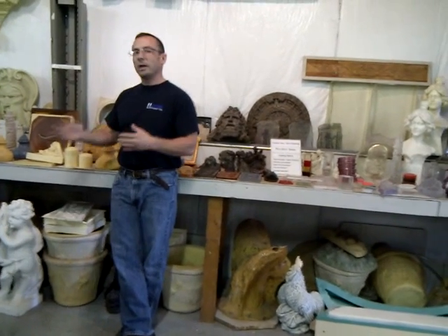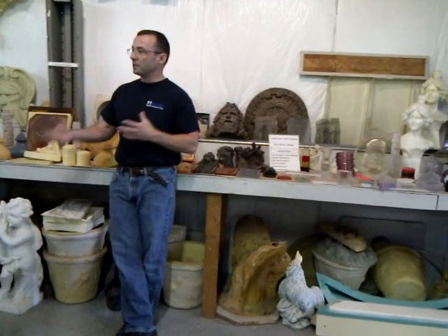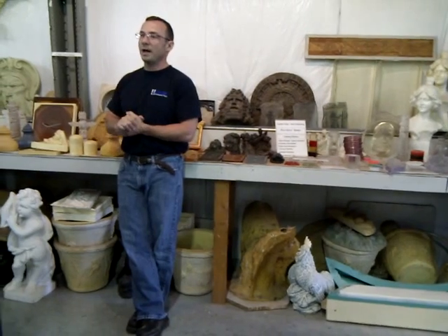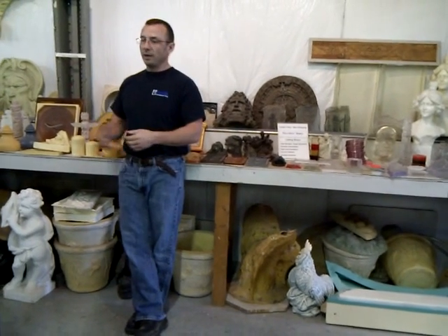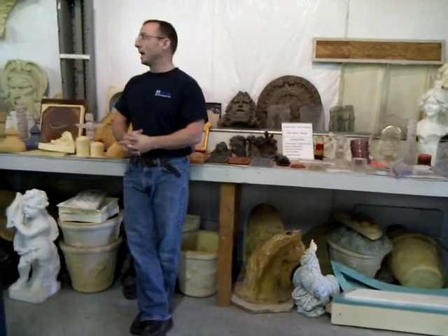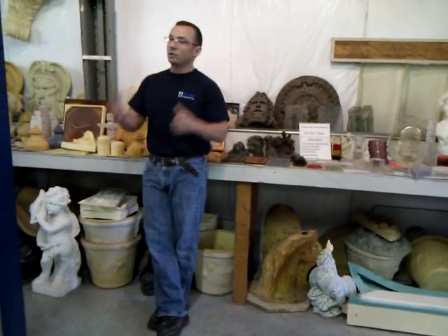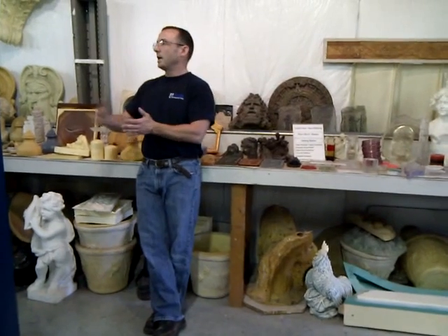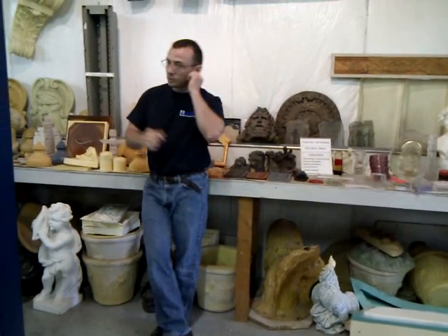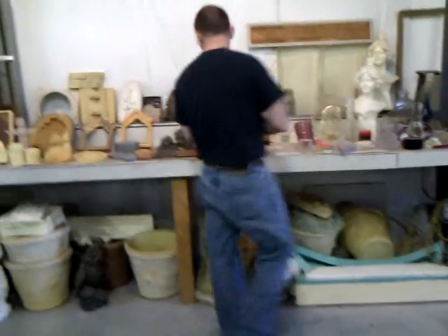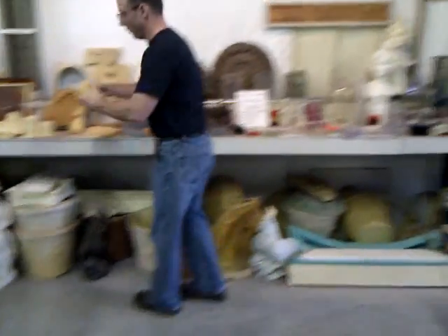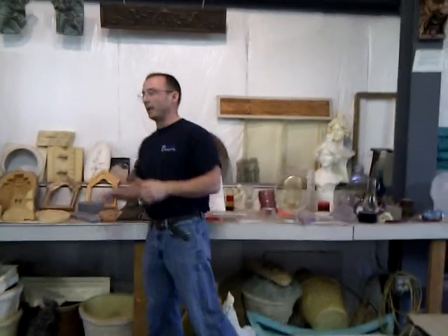So depending on what you're trying to do, there are different density foams. So let's say you want an 8-pound density casting, you don't want to use R8 because that's the free rise density. You might want to use R5 and pack it to 8 pounds to get a good part. And we'll demonstrate a couple of different foams there. The flexible foams are just that. They're foams kind of like a Nerf football or a couch cushion type foam. And again, same thing with a 3-pound and a 5-pound density product.